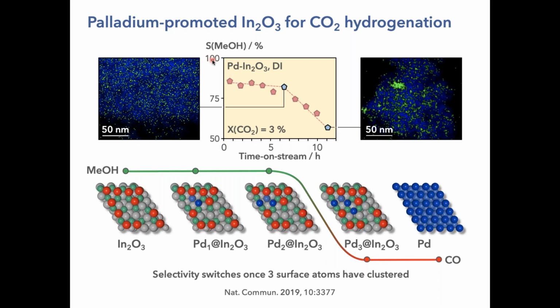What we have found, and this still is a result of DFT analysis, is how big the cluster of palladium can be so that we don't manifest the reverse water gas shift that you will have on a pure palladium system. And actually, this was done by studying activation energies for either methanol production or CO production on the different models. And what we found is that the border between selective behavior to methanol and unselective behavior to methanol, or selective behavior to CO, is 1 atom thick. So a dimer on the surface, which will be actually a trimer on the material, is still highly selective to methanol, but having a tetramer already leads to nanoparticle type behavior, leading to reverse water gas shift.